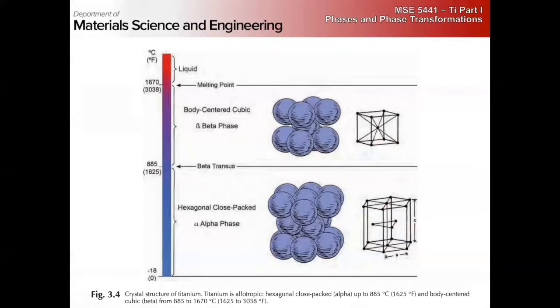So even in the high temperature phase, deformation is not super straightforward because you have a mess of different slip systems. And you've got a lot of plastic and elastic anisotropy in both systems. You also have thermal anisotropy, thermal expansion anisotropy in the HCP phases.